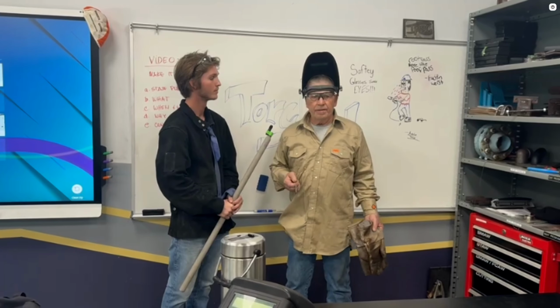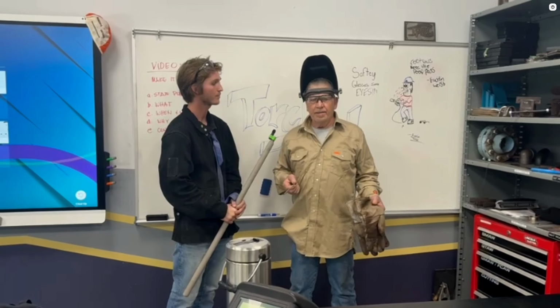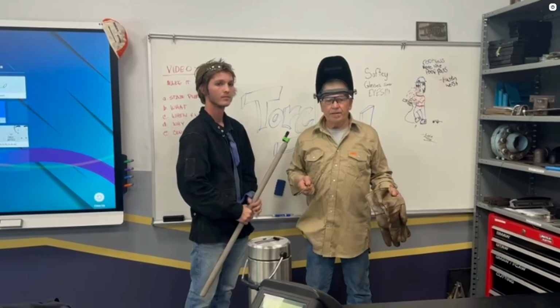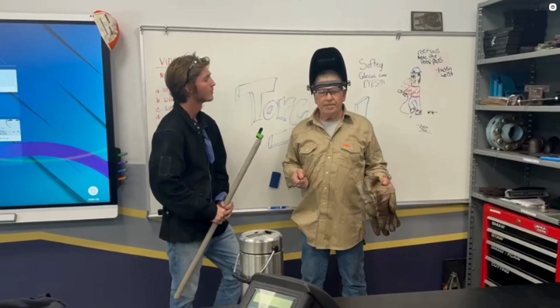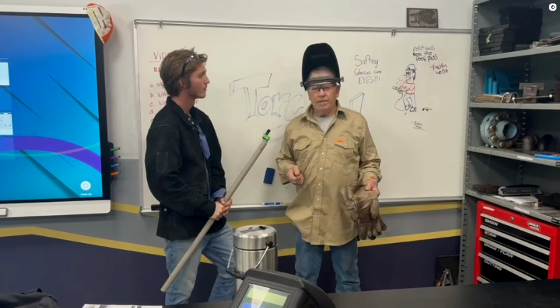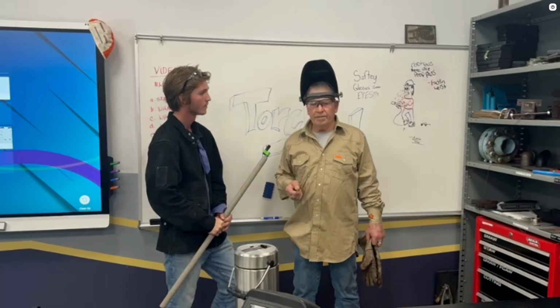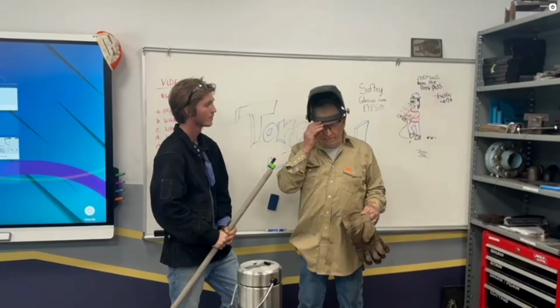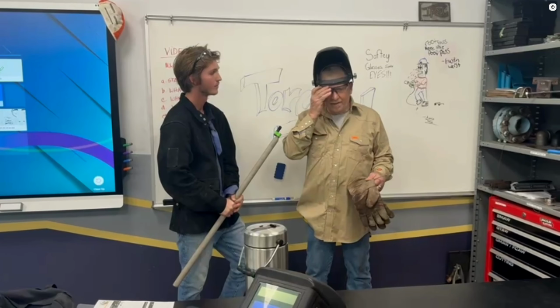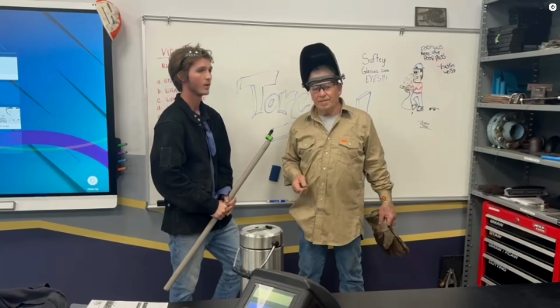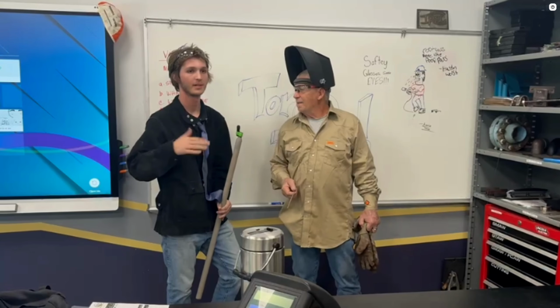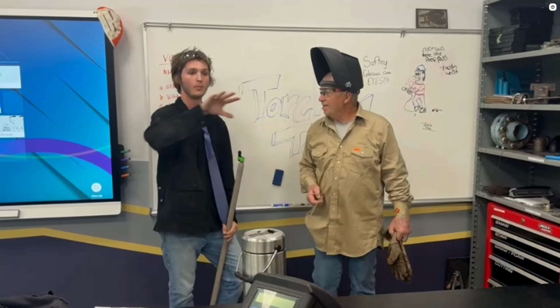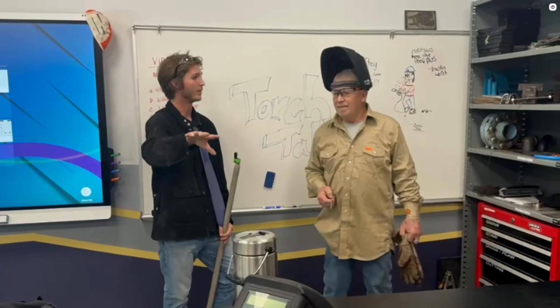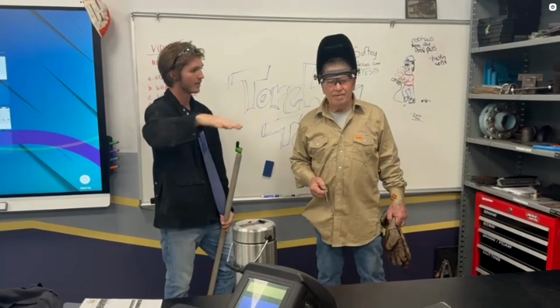Then we've got the fill freeze group. They're basically the middle ground, which would be 6012, 6013 rods. The puddle solidifies at a moderate rate, making them easier for beginners to control. They can be used in basically any position and have a much smoother bead appearance. They're pretty good on sheet metal or general fabrication too.